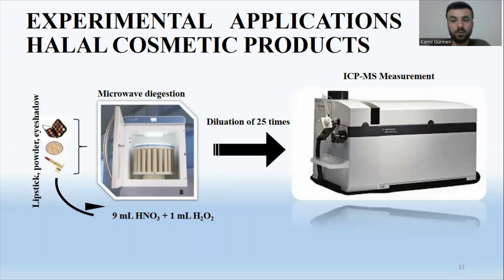Three different products were dissolved in a mixture of nitric acid and hydrogen peroxide at the specified rates and transferred to a Teflon container and added to the microwave system. After digestion in the microwave system for 35 minutes at 1800 W at 210 degrees, a total of 13 heavy metal analyses were carried out in the ICP-MS system for the samples diluted 25 times for heavy metals determination.